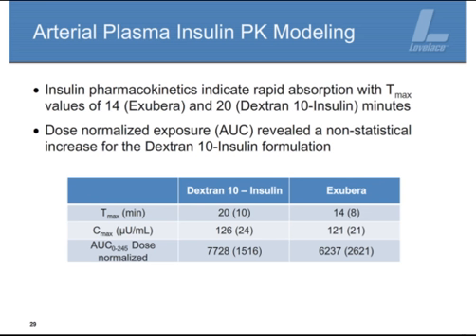And then we get into the pharmacokinetic modeling. As you see in this table, probably the most important part of the pharmacokinetic modeling is the Tmax, the time at which the maximum concentration is achieved. We're very close for these two formulations, with a Tmax of 14 minutes for Exubera and 20 minutes for the Dextran 10 insulin formulation. Coupled with that is the Cmax, the maximum concentration achieved in the systemic plasma. As you can see from the table, they're both at about 120 to 125 microunits per mil, meaning that the speed and the completeness of absorption were very similar. That speaks to the quality of the formulations and the similarity between them in this inhalation delivery, and that they were likely deposited very homogeneously throughout the lungs of these animals.